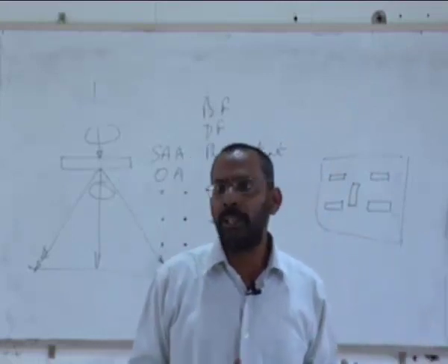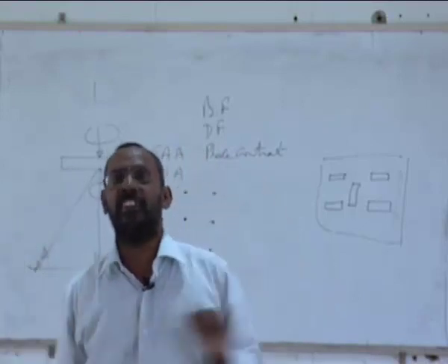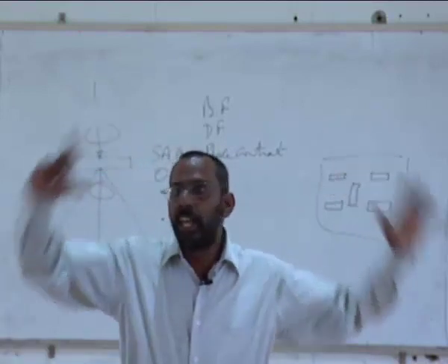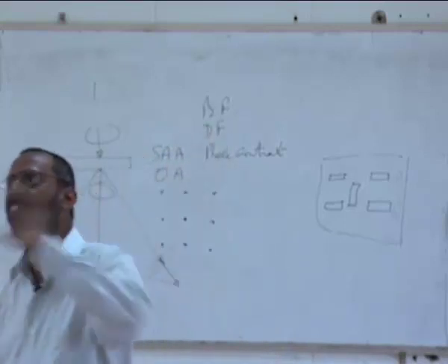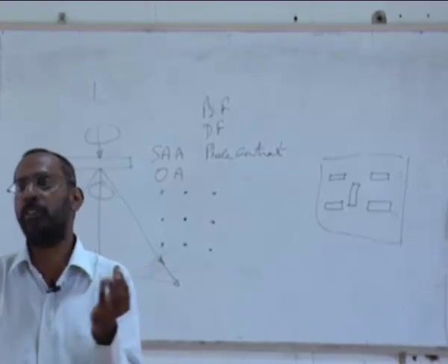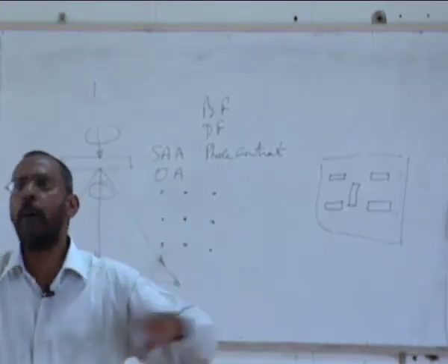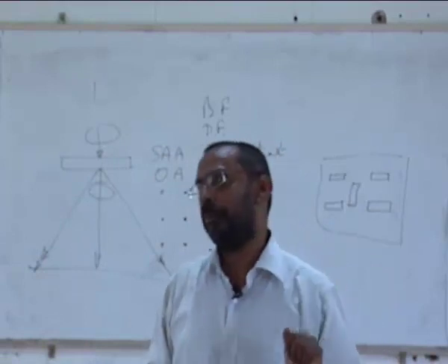But the problem is the sphere may not have the lowest strain energy, because in a solid state precipitation, you need to bother both about surface energy and strain energy. So the system will choose such a shape of the precipitate which will have a lower combination of both. It wants to minimize the combination of these two energies.